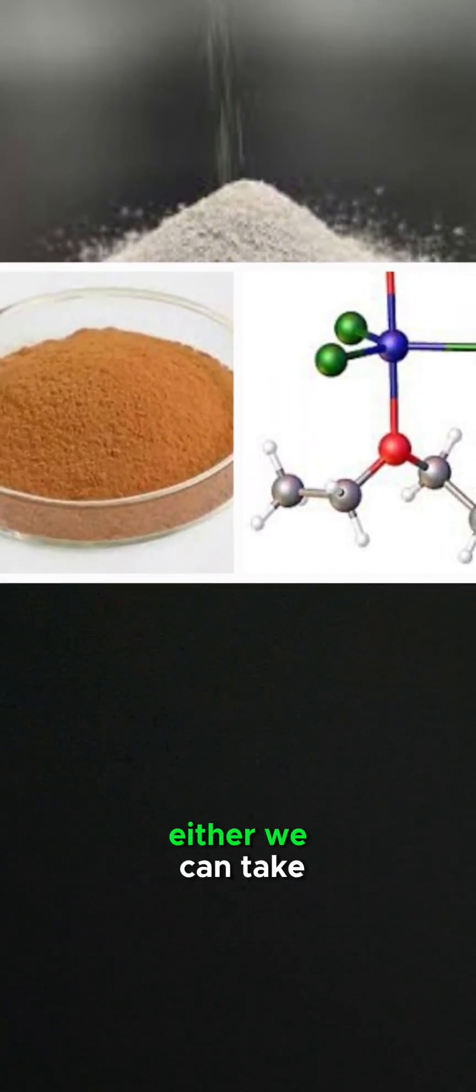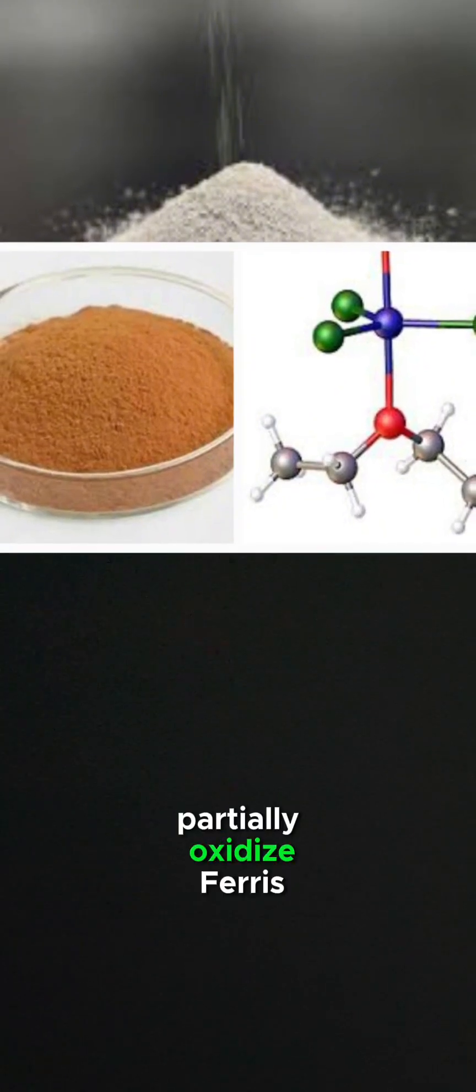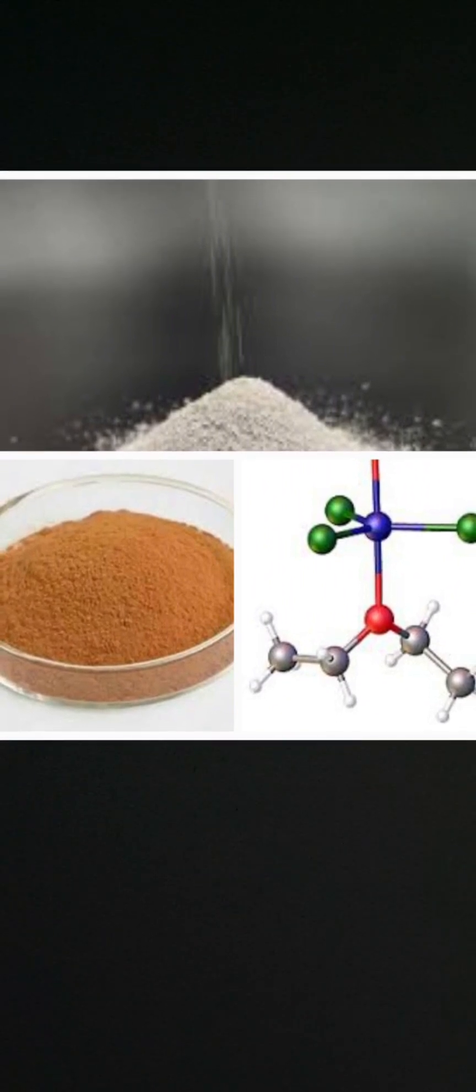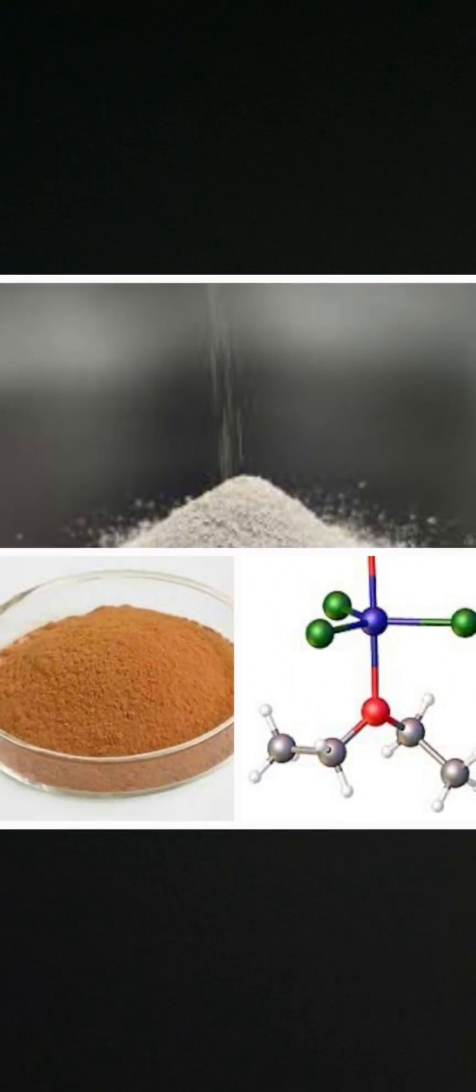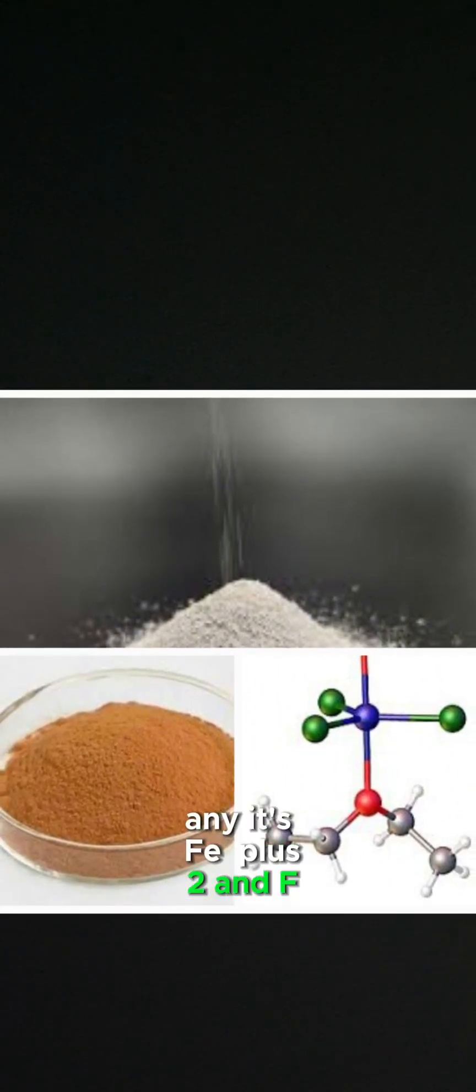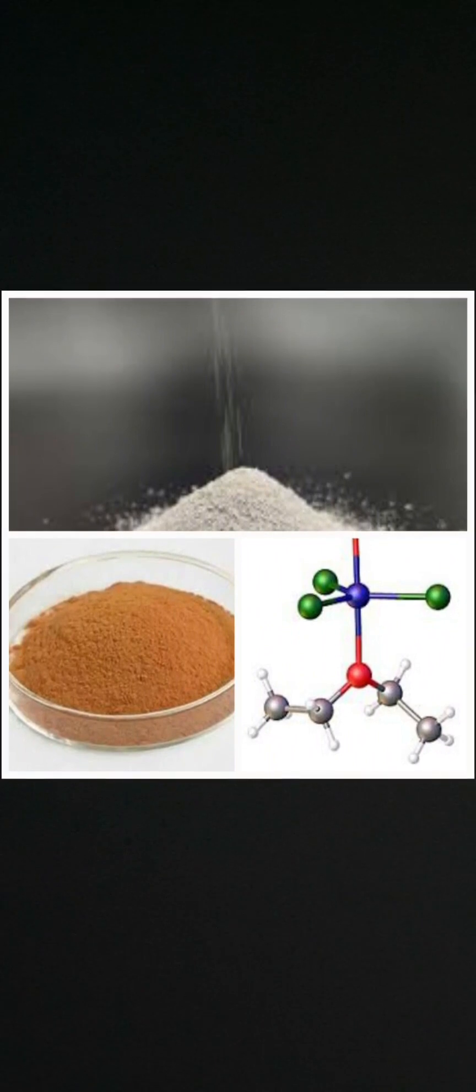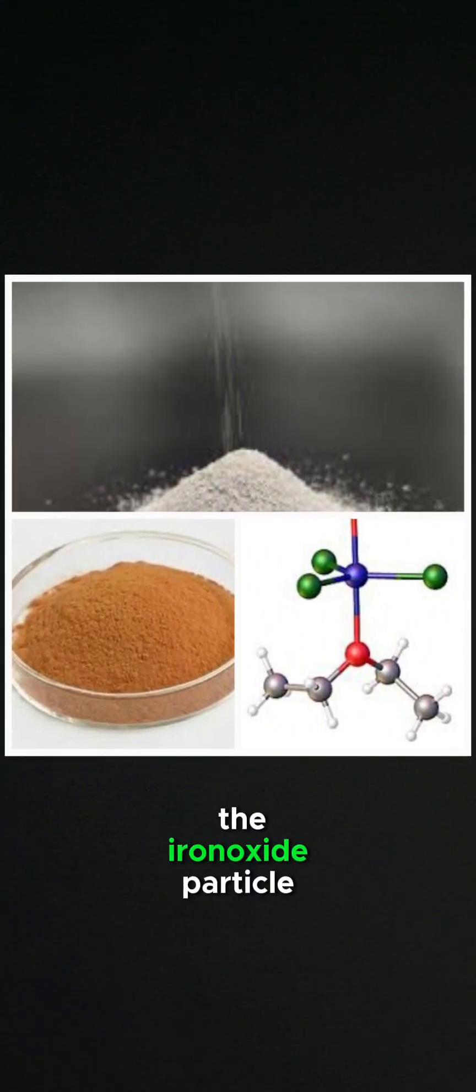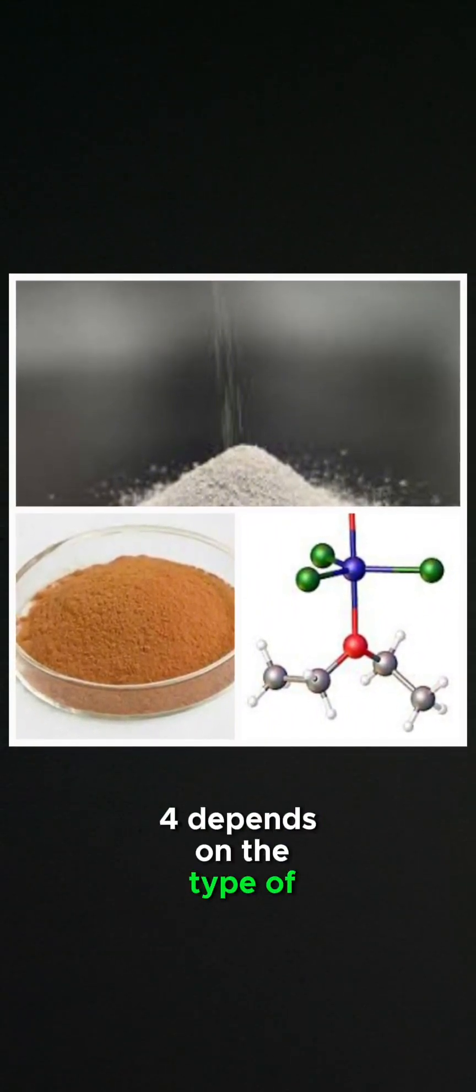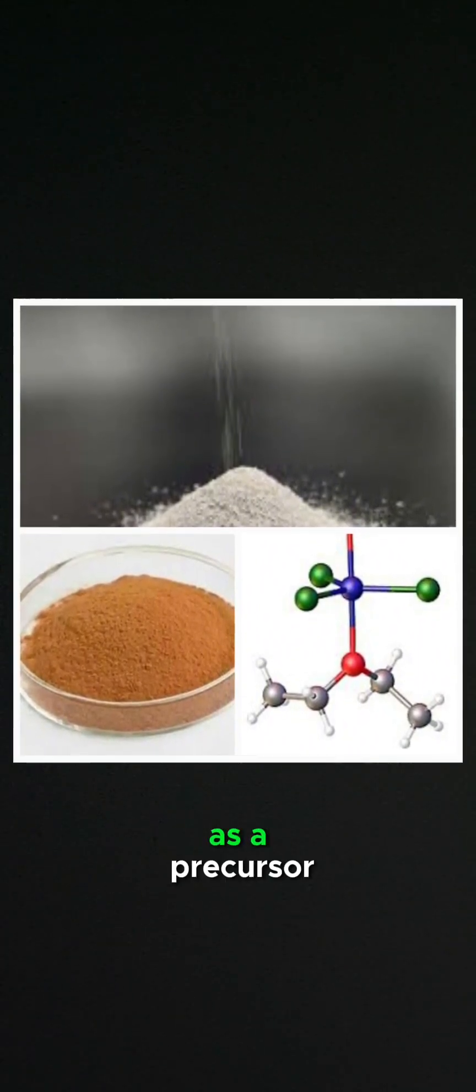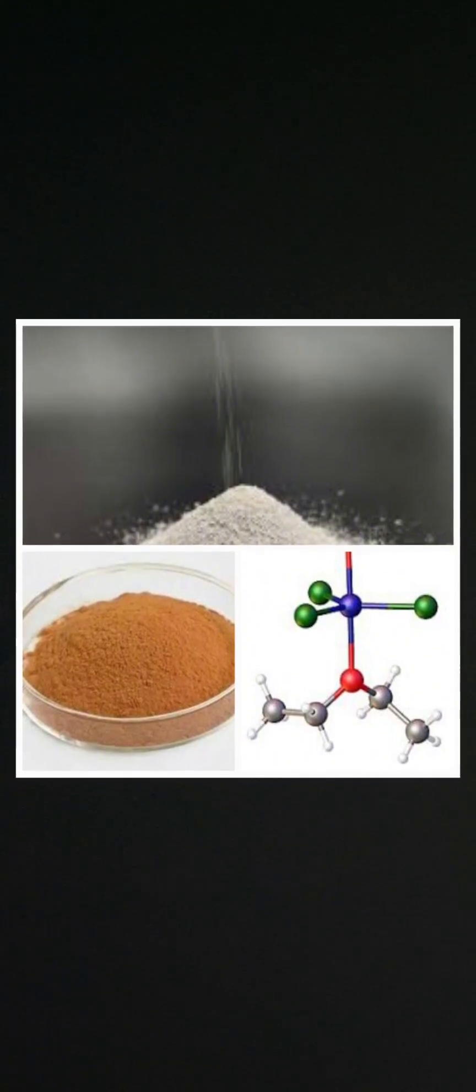As per certain papers, there are two main approaches for the synthesis of magnetic nanoparticles. Either we can take partially oxidized ferrous hydroxide suspensions with different oxidizing agents, or add stoichiometric mixtures of Fe2+ and Fe3+ in aqueous media, which yields spherical magnetic particles that are homogeneous in size. The size and shape of the iron oxide nanoparticle (Fe3O4) depends on the type of salt used, so we have to be very careful about what salts we use as precursors, whether ferric or ferrous, and the pH value.